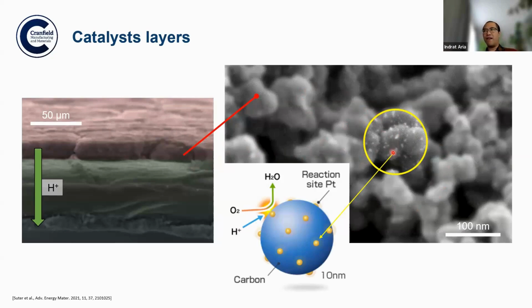Carbon is very cheap. However, this carbon is decorated by platinum. The platinum is the one that's very expensive. So the catalyst itself is the platinum, not the carbon. Carbon is just the structure to hold the platinum catalyst. Carbon is electronically conductive, hence it's a good structure to hold the platinum.